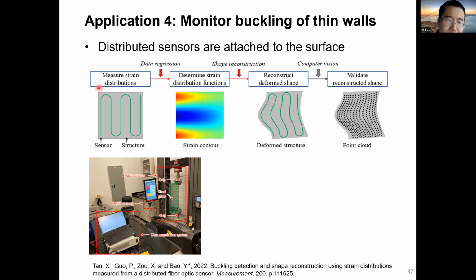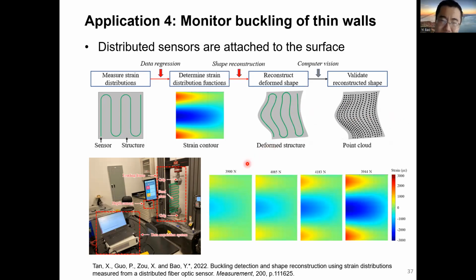So, for example, if we have thin aluminum plates, we can deploy sensors in this pattern, and we can measure the strain distribution. So, by converting the strain distribution into the out-of-plane deformation of the plates, we were able to estimate the buckling severity. And we also validated this measurement results using point cloud data from computer vision measurements. And as you can see, when the applied load increased, we were able to detect the initiation and the development of buckling.